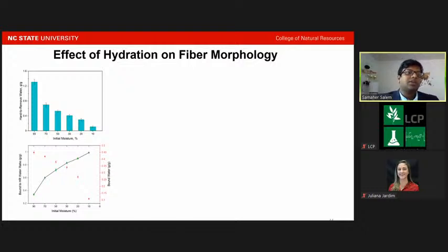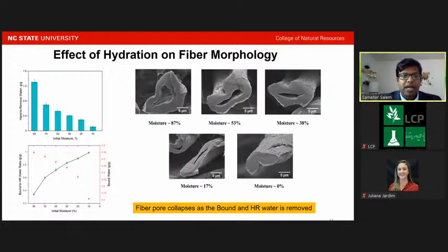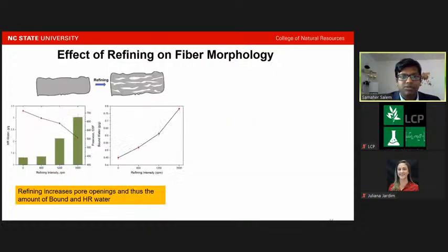So we also measured how the hydration affects the fiber morphology, and we could find that the hard to remove water and the bound water increase with the increase of the initial moisture content. And when we try to remove this moisture content, we could see that the fiber pore wall decreases as the moisture content is decreased. And this SEM image shows step by step how the fiber is collapsing as we remove the bound water and hard to remove water.